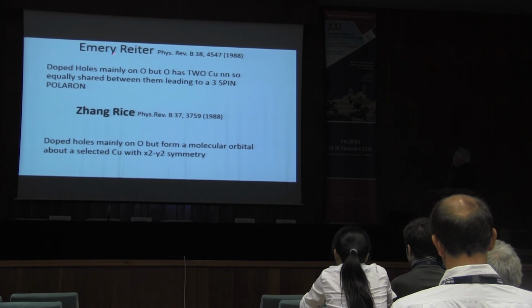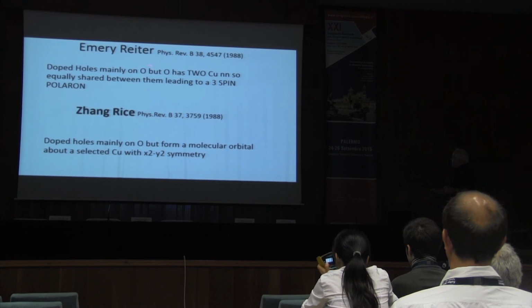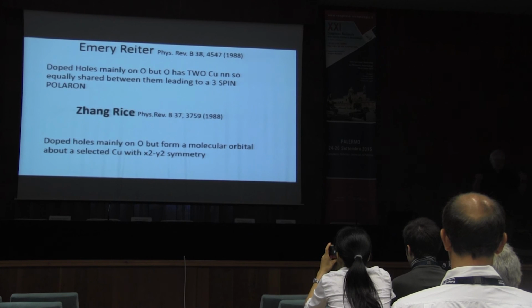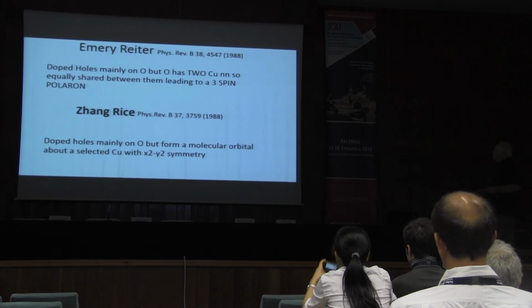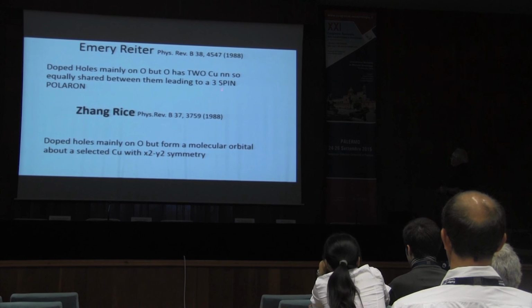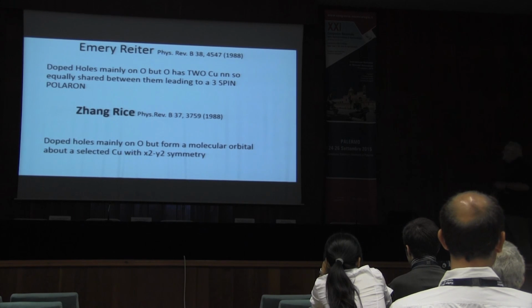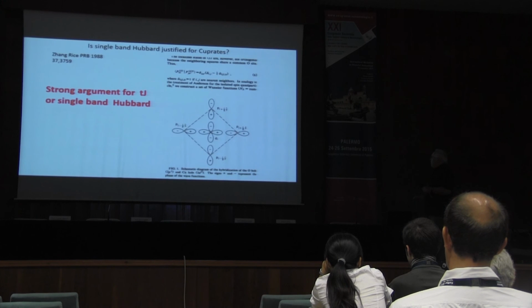And there were 2 other papers at the same time. One of them was by Emery and Reiter, which said that, well, look, the oxygen in this structure is actually between 2 coppers, so it should be equally shared between the 2 coppers. And then they showed that this would lead to a 3-spin polaron, and I'll come back to that later. Whereas the Zhang-Rice story was that, well, the doped holes go mainly on oxygen, but they form a molecular orbital of the 4 oxygens around a single copper, which they've chosen somehow or other. And that orbital would have x squared minus y squared symmetry about that copper, mixing strongly with the one hole that you have on the copper x squared minus y squared orbital. And that would form a singlet state with a very strong exchange interaction.